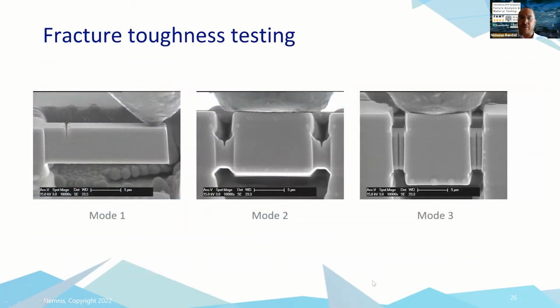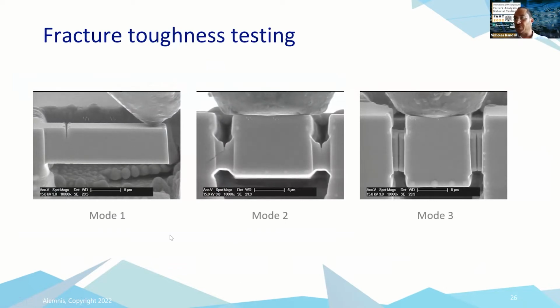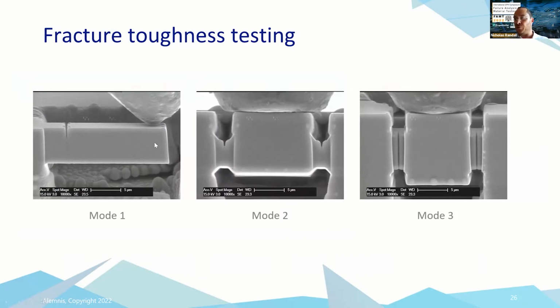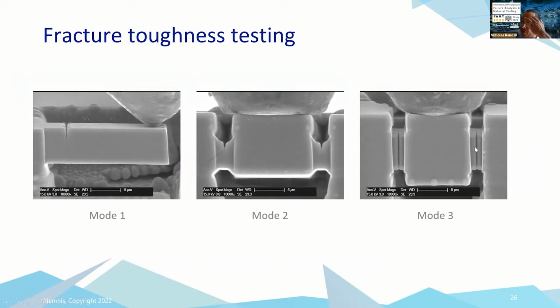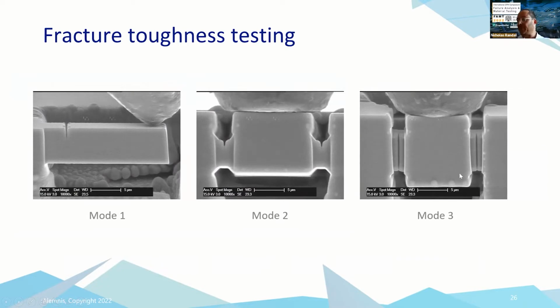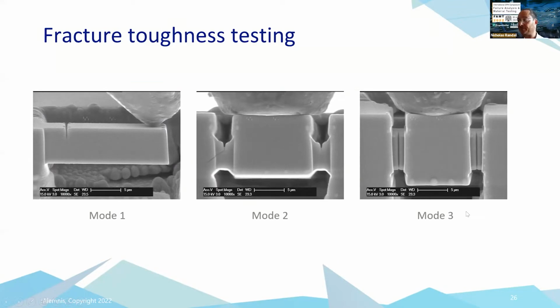Okay. These are some dedicated structures made by focused ion beam for fracture toughness in 3 modes. So single beam with a pre-notch, so mode 1 deformation, right? Mode 2, so going against the crack axis, and you can see small cracks being produced here. This is all silicon material. And mode 3, going actually perpendicular to the axis. So these can be used for specific fracture toughness calculations.